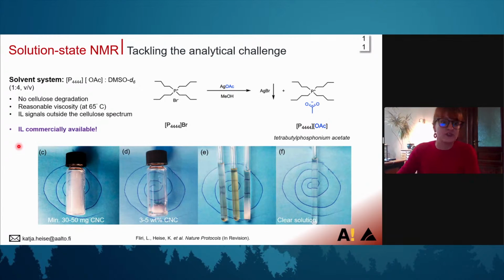So in the dissolution procedure, we use our 30 to 50 milligrams of CNC sample, or cellulose nanocrystal sample. We dissolve it mostly overnight at 65 degrees already under stirring. Then we check, and when the solution is not yet really clear, so what we're aiming for, of course, are clear solutions. And then we know we can go to analysis.